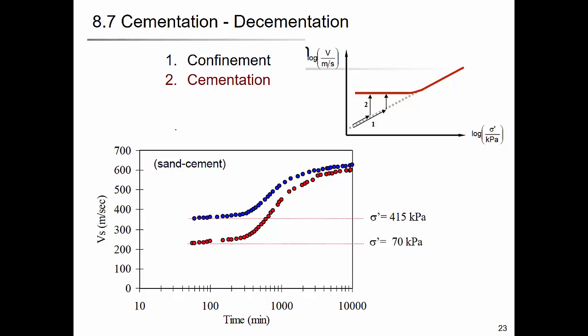So let's look at the real data. We had the sand and cement mixture here, which was under 70 kilopascal vertical loading. And as they cure, you can see that we have an increase in wave velocity to around 500 meters per second. Right? Before it was about 200 meters per second. And when you apply more stress before curing the cement, they started from around 300 meters per second, and then they also approached around 500 to 600 meters per second. You can see that the final wave velocity was more controlled by the cementing agent concentration. So they approach a similar value.